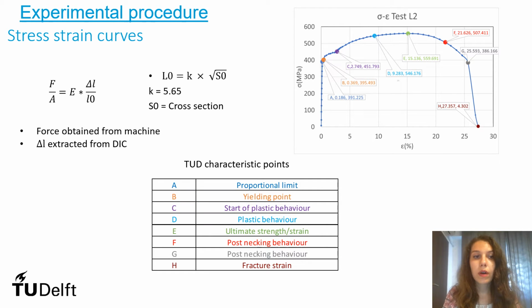Furthermore, I used the force that I obtained from the machine and the displacement that I obtained from the digital image correlation, transferred the displacement to strain by the gauge length, and ended up getting the stress-strain curves.